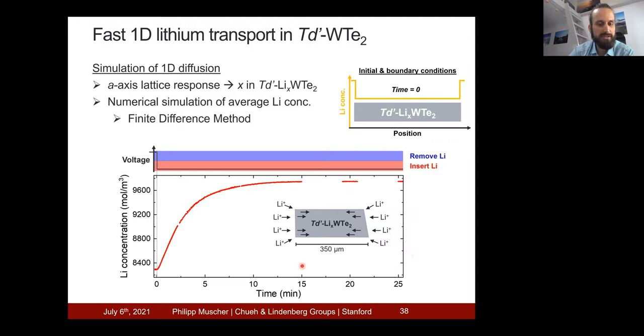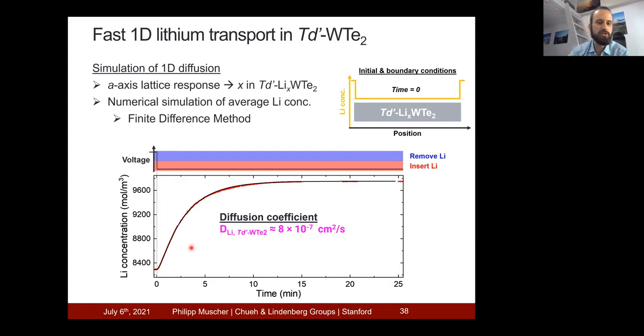So with this simulation, I can completely replicate the experimentally seen concentration profile. The simulation is shown in black over here, and the data is shown in red. From this simulation, I can extract the diffusion coefficient of lithium in TD prime tungsten ditelluride. And that diffusion coefficient is 8 × 10⁻⁷ centimeters squared per second.